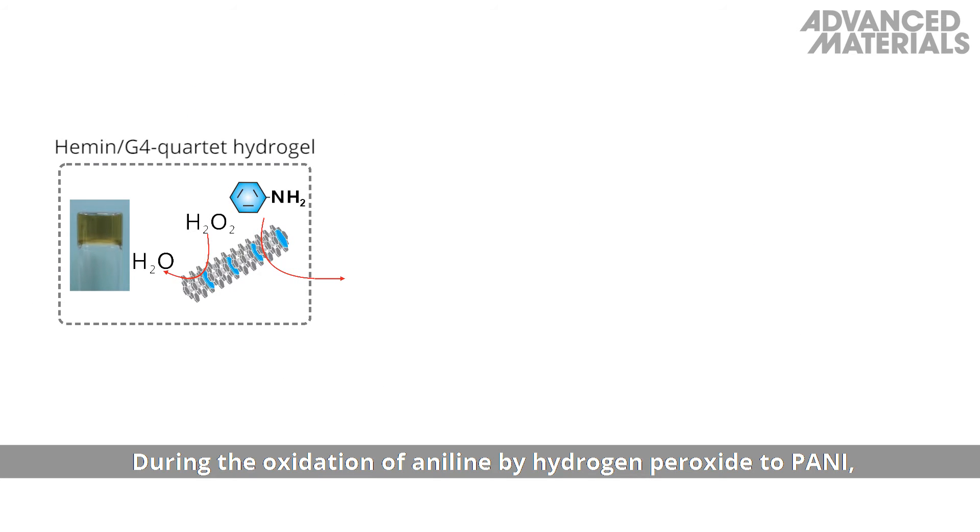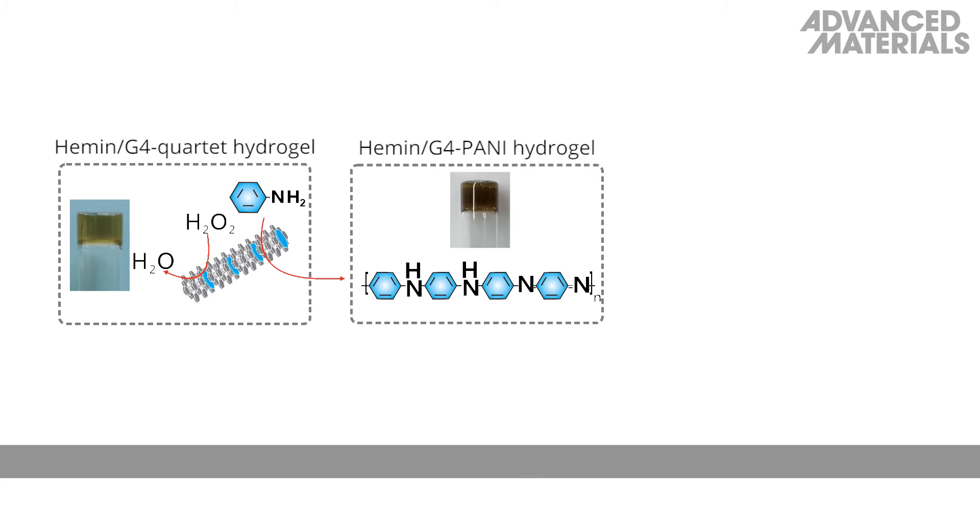During the oxidation of aniline by hydrogen peroxide to PANI, an approximately 2nm thick layer of PANI was deposited on the catalytic hydrogel matrix.